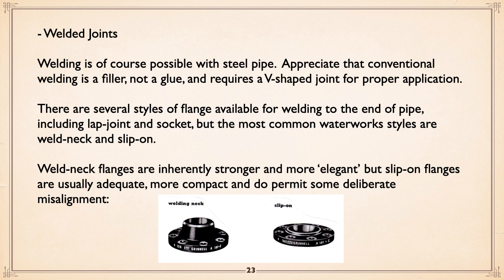There's different flanges available for welding to the end of a pipe, including lap joint and socket, but the most common waterworks styles are either weld neck or slip-on. Weld neck, shown on the left in the diagram, is inherently stronger and more elegant. It looks nice. But slip-on flanges are usually adequate, more compact, and do permit some deliberate misalignment. It's quite common with slip-on. You've got the pipe there; it's right up or very close to the flange on the pump, and you take a slip-on, put it up against the flange on the pump, and then loose bolt it, and then weld it. And if there's a bit of an angle, it's there forever. Okay, fine and dandy.